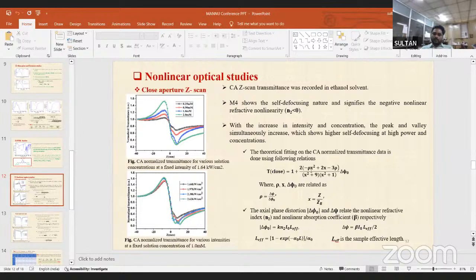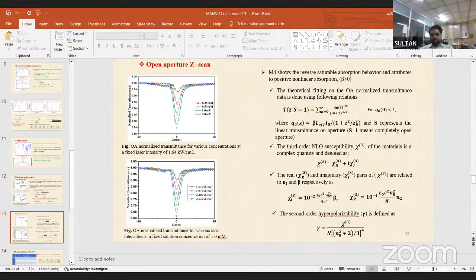Here x equals z by z0, where z is the position of the sample and z0 is the Rayleigh length, and rho is equal to delta psi over delta phi. Delta phi is the nonlinear phase shift due to the nonlinear refraction, and delta psi is the phase shift due to the nonlinear absorption. L effective is the effective length of the sample, given by this relation. For calculating the nonlinear absorption, we recorded the open aperture Z-scan transmittance at various concentrations and powers, and we found a valley configuration in open aperture. So our molecule shows reverse saturable absorption, and the theoretical fitting is given by this relation.